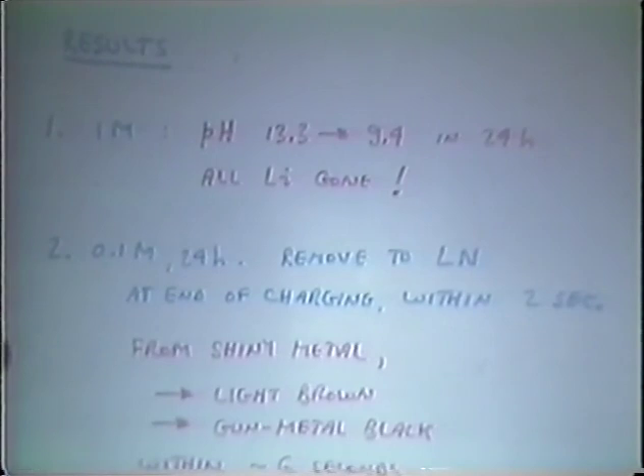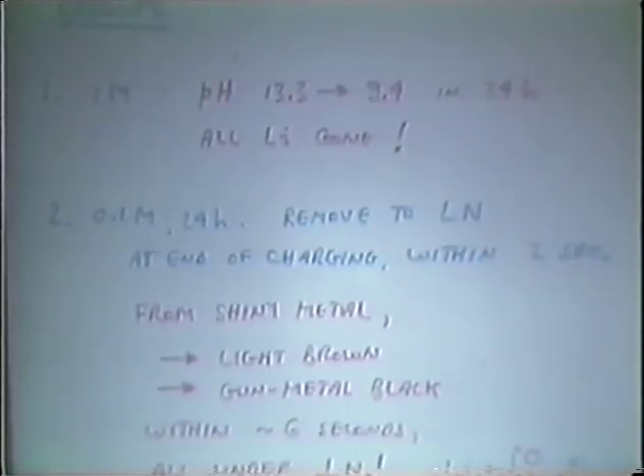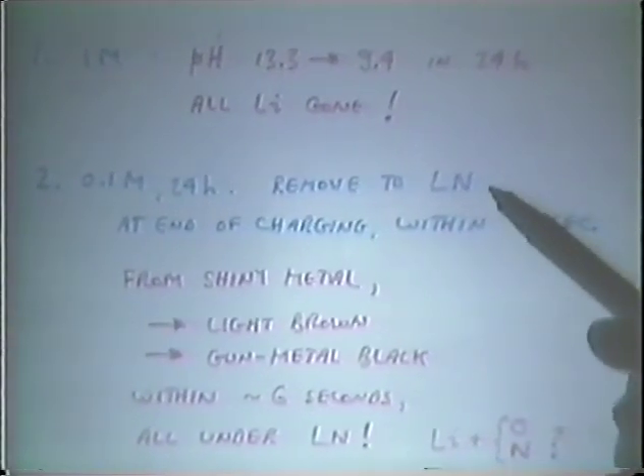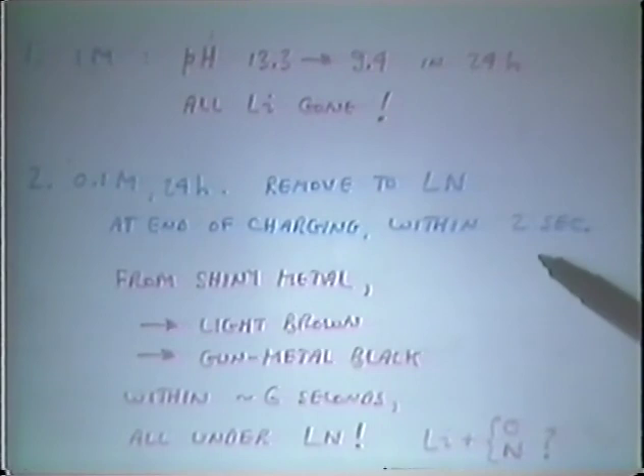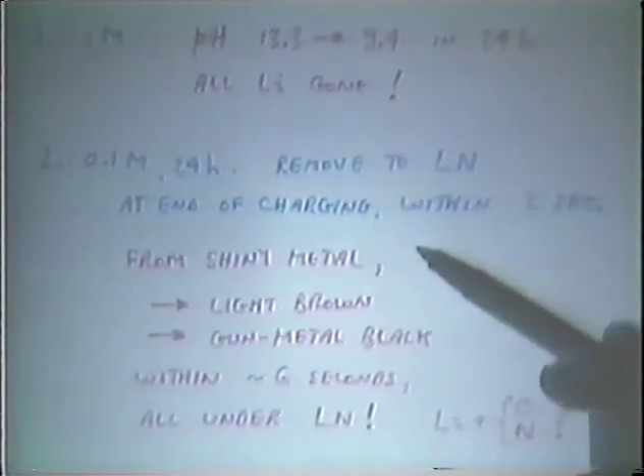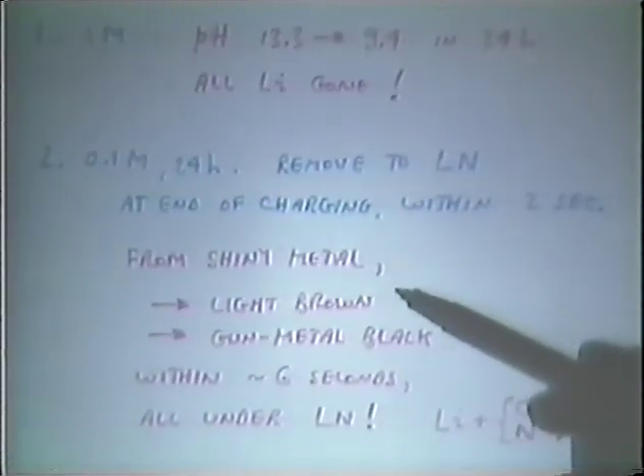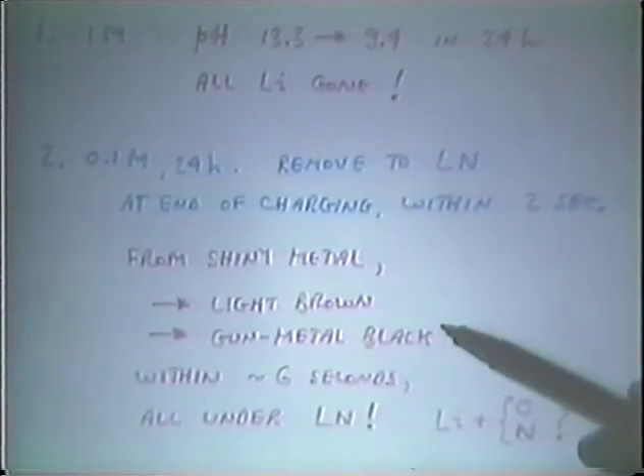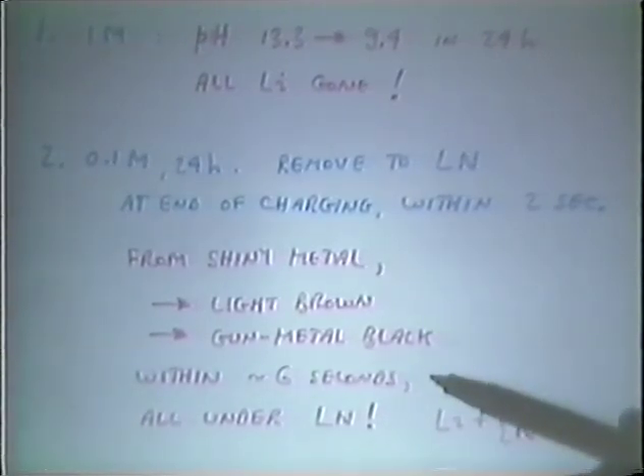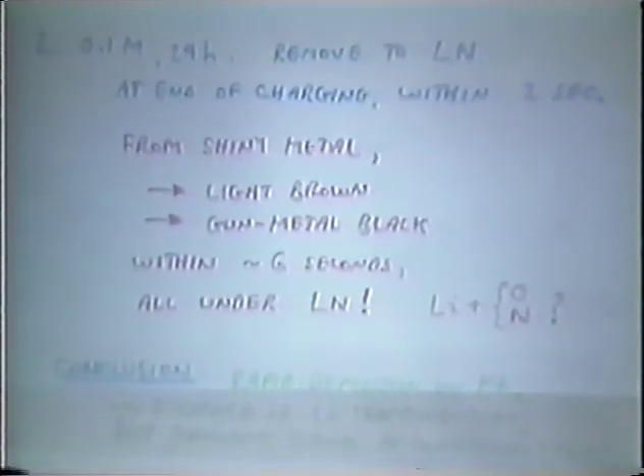This is with a platinum cathode, of course, not a palladium cathode. With a 0.1 molar solution, after 24 hours, we removed it and transferred it into liquid nitrogen within 2 seconds after cutting the current. The shiny metal surface turned first light brown and then gunmetal black within about 6 seconds, all of this taking place under liquid nitrogen at 77 Kelvin.